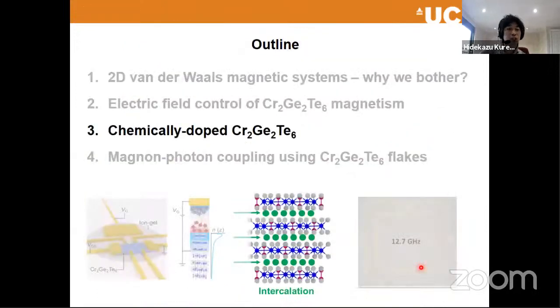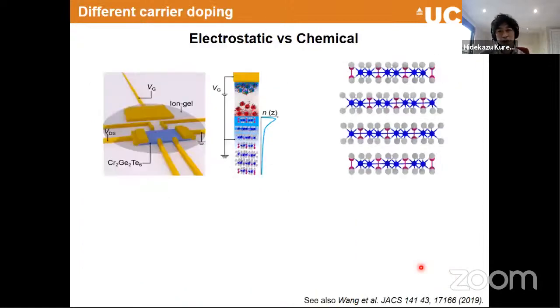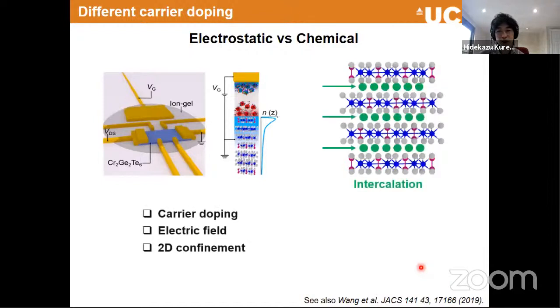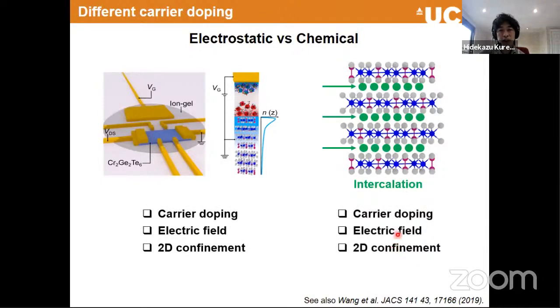And we can do the same experiment by a chemical doping method. The reason why we decided to do this is that with chemical doping, we can differentiate these three different effects. When we do the electric doping, we can create a charge. Also, we can create an electric field. And as a result, we can create 2D confinement. So we don't know which one actually provides the result we get in terms of magnetism.